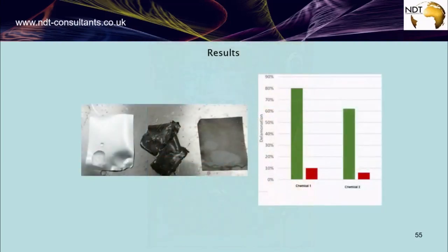So briefly, I'm going to show you here. As you can see in this picture, on the right side, you have a piece of this electrode material that we cut from a Nissan Leaf battery. So you can see the black material there is the active material, and it is bound on a piece of aluminium. Once we have treated this with ultrasound, on the left side there, you have the aluminium foil, which is very clean, which means we successfully removed the active material, which is in the middle there.